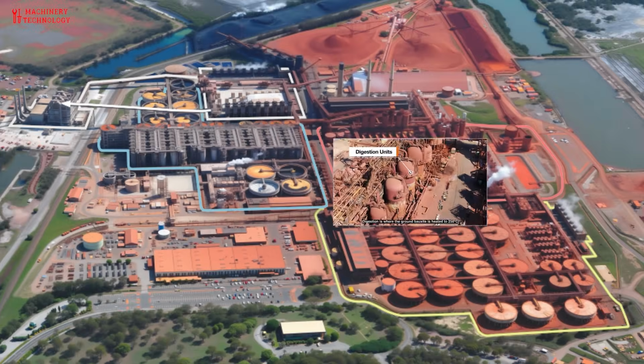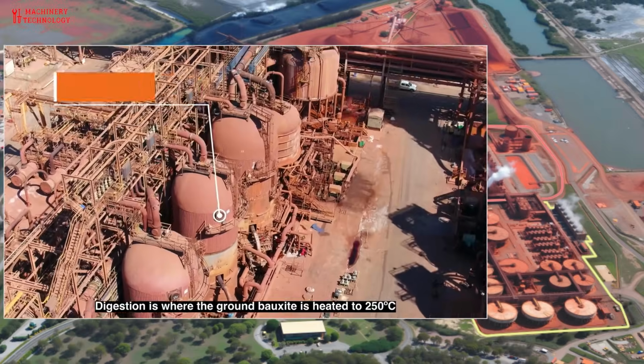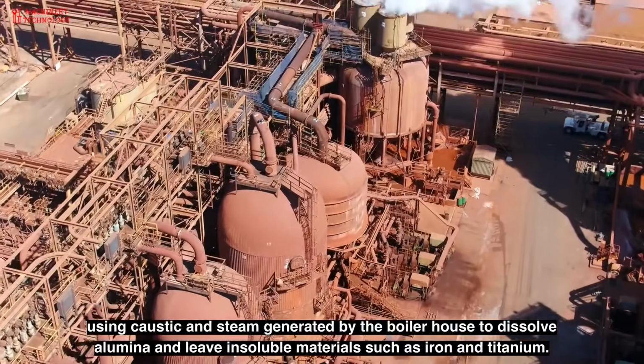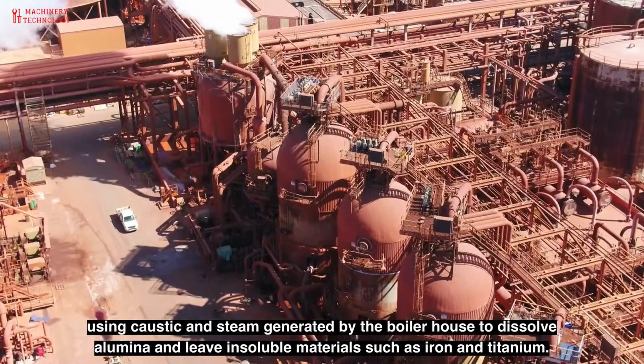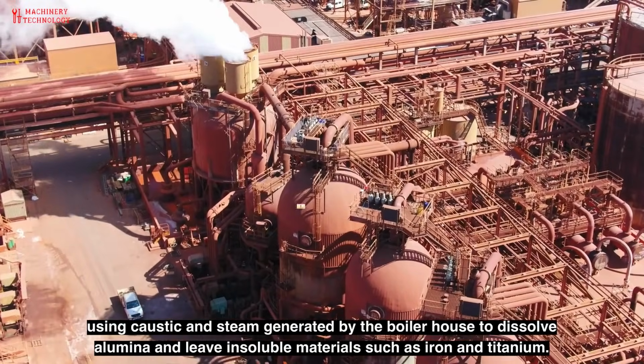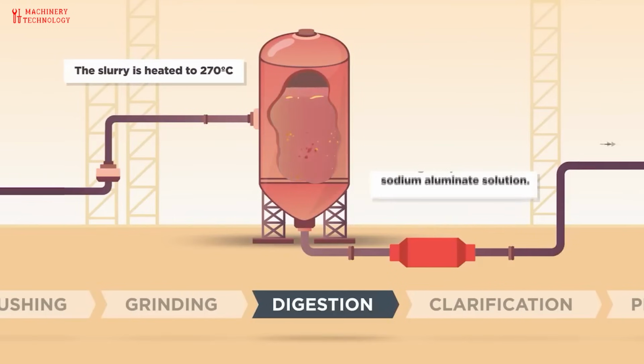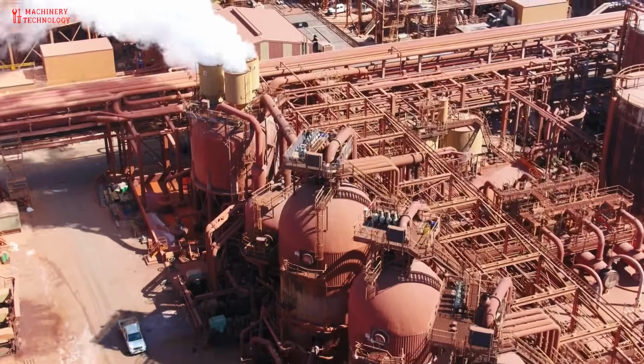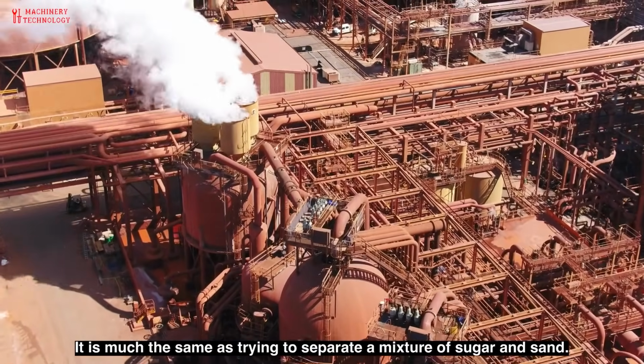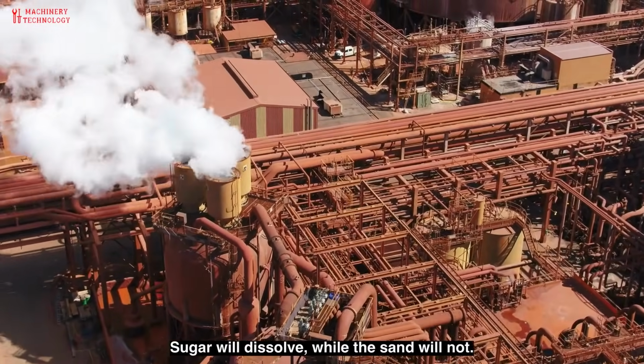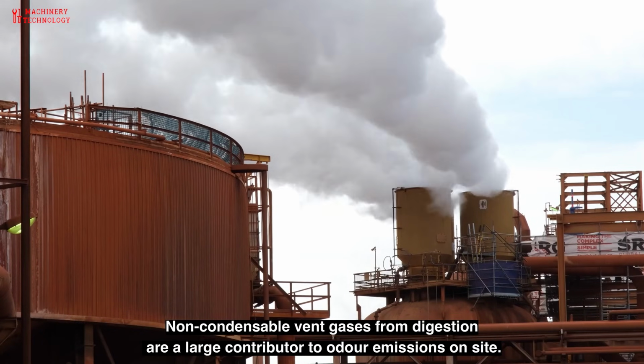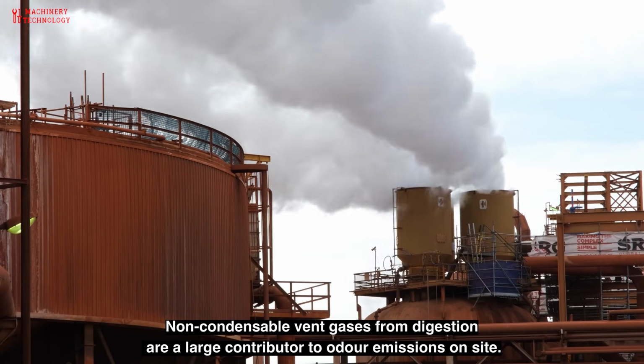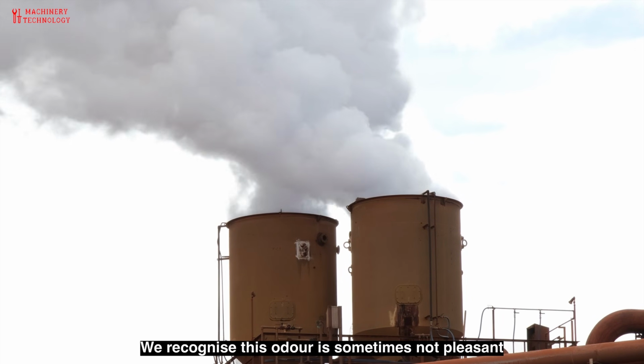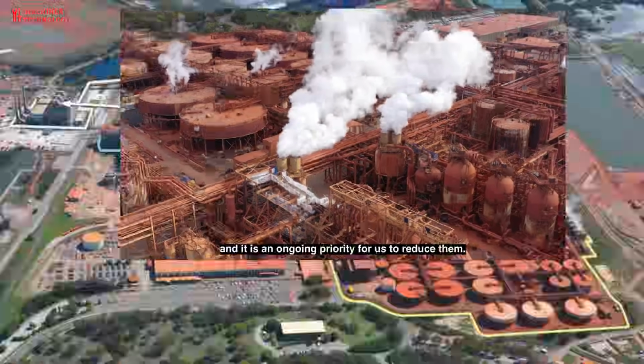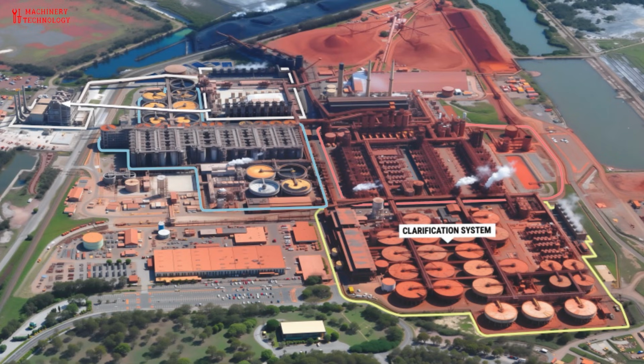In the digestion system, finely ground bauxite enters massive steel vessels with thick walls, engineered to withstand extreme pressure and high temperatures. Inside these sealed reactors, the slurry is heated to around 270 degrees Celsius. Under these conditions, hot caustic soda dissolves the alumina, forming a supersaturated sodium aluminate solution. Once digestion is complete, the liquid stream moves forward to the next system. With alumina now fully dissolved, the process shifts from chemical reaction to physical separation.